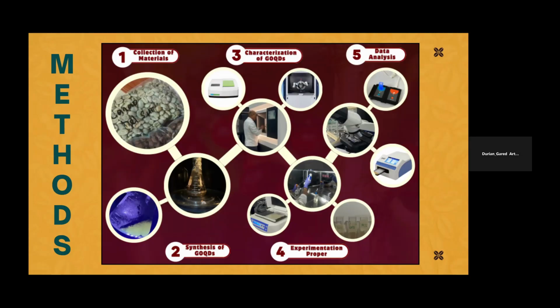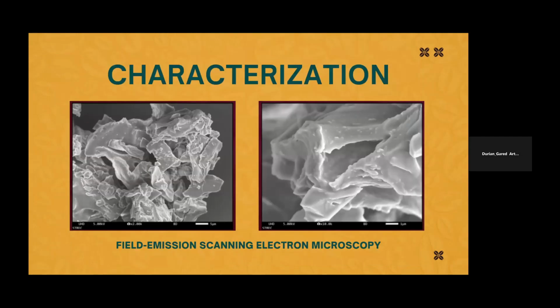Then, the green synthesized GOQDs were cooled to room temperature before being analyzed with a UV-Vis spectrophotometer, scanning the optimal wavelength range of 200 to 400 nanometers to assess their optical density. Afterwards, Fourier transform infrared spectroscopy, or FTIR, was performed to identify surface functional groups and absorption peaks. The GOQD samples were also subjected to in-depth characterization through X-ray diffraction analysis, energy dispersive X-ray spectroscopy, field emission scanning electron microscopy, and transmission electron microscopy, providing a detailed evaluation of their size, shape, crystallization, elemental composition, peaks, and nanoscale structure features. Here we have our FESEM images, which provide clear morphological evidence supporting the production of graphene oxide quantum dots, or GOQDs.